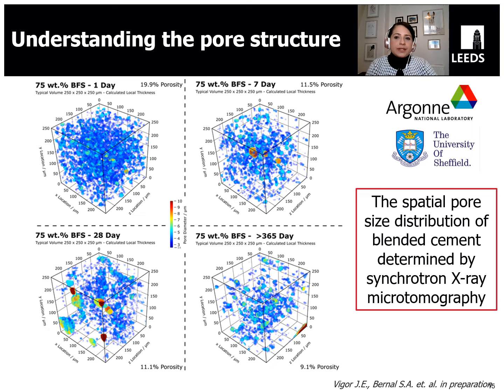But we know that carbonation is not just a chemically controlled mechanism, it's also a diffusion controlled mechanism. So there is tremendous interest, of course, to understand the pore structure of this type of materials. In this opportunity, these are micro CT reconstructions for blended Portland cements with high volumes of blast furnace slag as a function of curing time. These are not exactly for alkali-activated materials, but I just wanted to show these beautiful reconstructions by James Vigor, who also has been working with me and others for many years in this area.